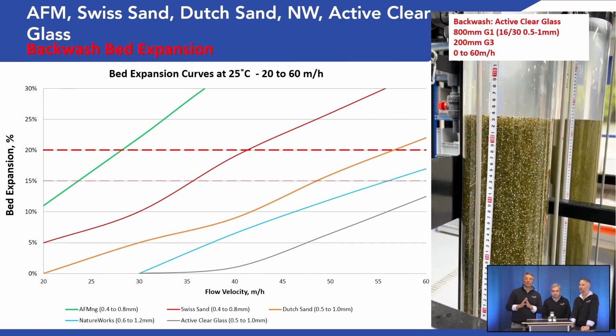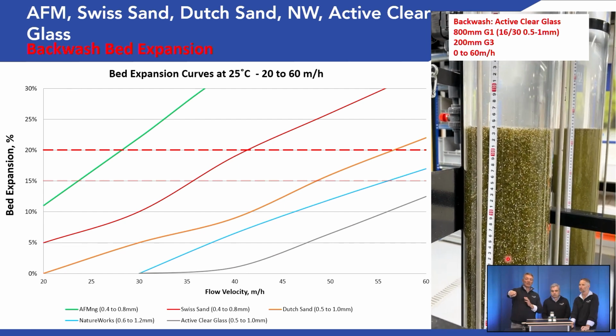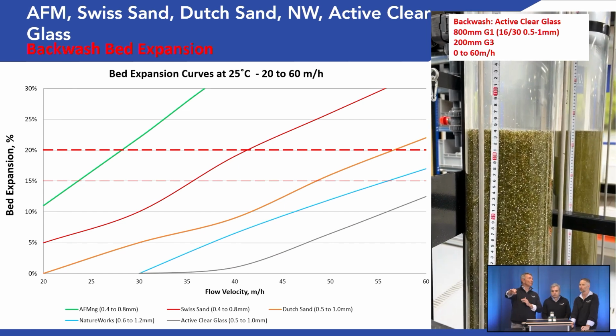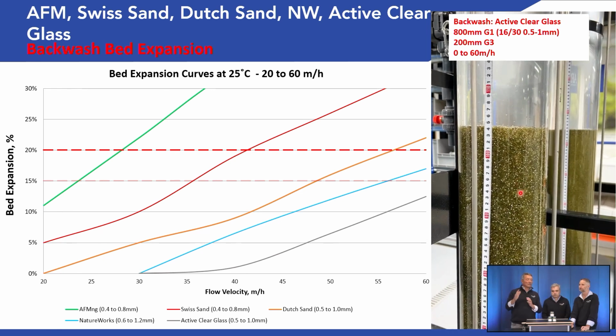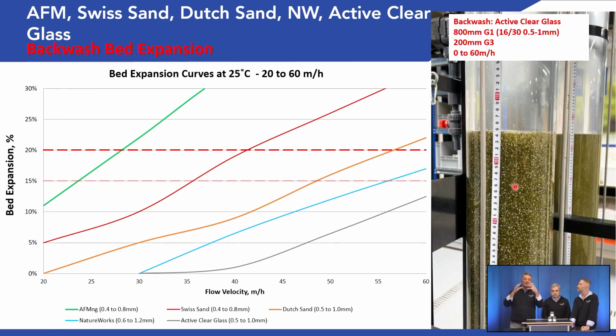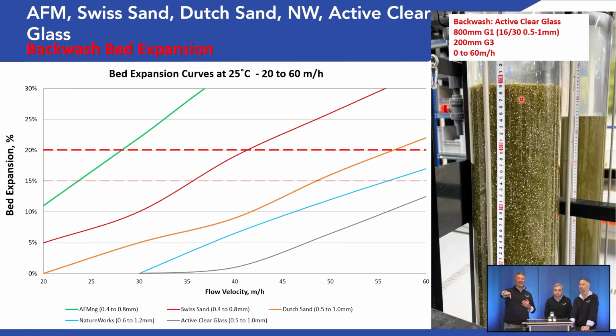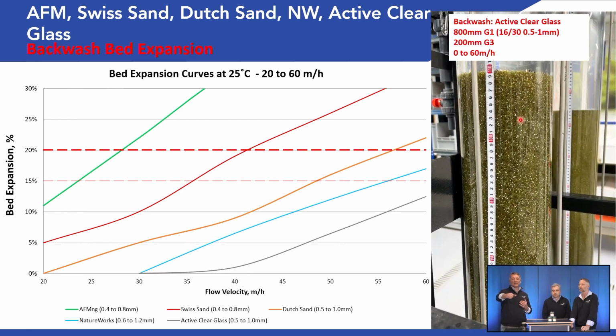But what you also see is that the picture is not changing. You don't have fluidization. What is fluidization? Fluidization is this dance between the particles, where they rub off each other, which releases the particles. And it is absolutely important that you have this. Now we are at 60 meters per hour, and you see a little bit of movement. It's bed expansion, but it's no fluidization. Very little, yeah.